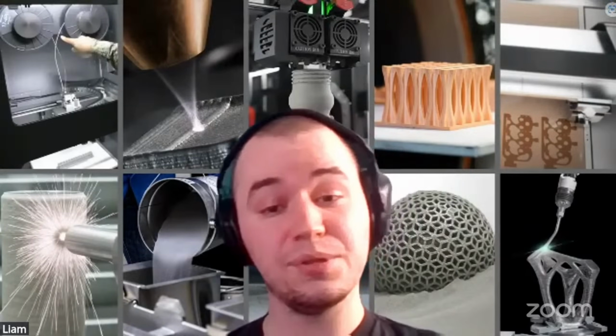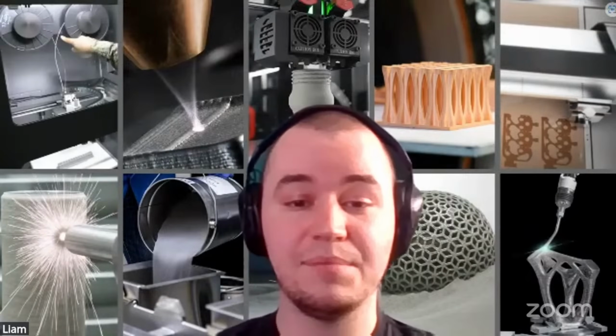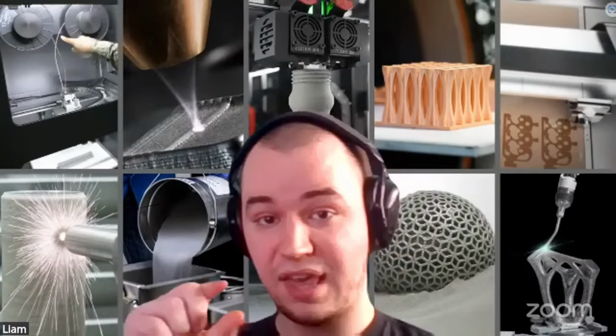What is the resolution of a product like that? It does depend on the printer. And so the maximum resolution would be whatever the size of the particles is. And that is something that is technically possible, but is incredibly difficult to practically achieve. And so oftentimes the resolution is set to be roughly the same as the spot size of the laser. So the size of the laser melt pool will be the resolution. So if you do a layer that is as thick as the melt pool, and that can be thousands of particles thick, depending on the size of the particle, then that's going to be your thickness of layer, and thus your Z height resolution.